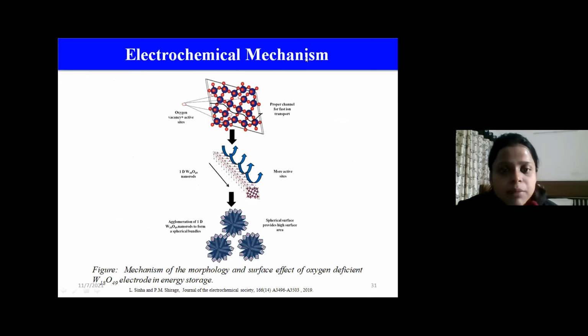So the mechanism that we have understood from our analysis is the oxygen vacancy. It acts as an active site for the electrolyte ions to uniformly interact with the electrode material. And the one-dimensional nanorods have a larger number of active sites. The agglomerated form gives spherical bundles of these nanorods, which provide a high surface area to the nanomaterial and also contribute to the stability.